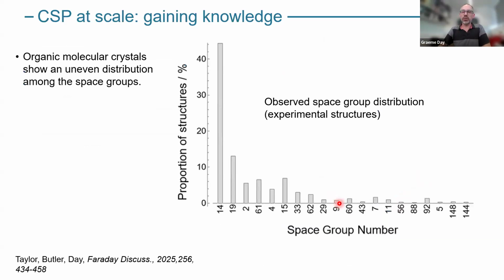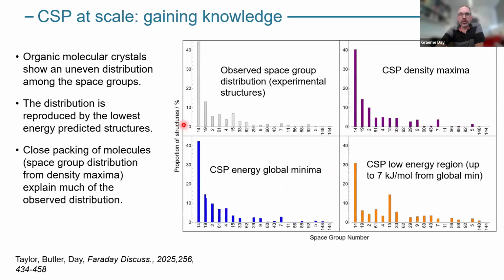Another thing we looked at is the observed space group frequencies of organic molecules, which we know is very biased towards a handful of space groups, P21/c, P212121. So this is the distribution of space groups that's observed experimentally. And if we look in our CSP data sets, we can look at a few things. We can look at the distribution of the global energy minima in terms of their space groups. And what we find is that it reproduces the observed space group frequency in experimental databases. So we're getting that agreement at least.